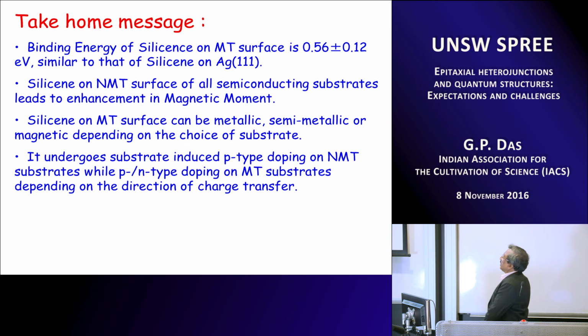So what is the take home message for this? The take home message is the following. The binding energy of silicene on metal terminated surface is coming out to be approximately 0.56 plus minus some error bar. Okay, and the corresponding value for silicene on silver 111 was 0.52. So it is close. Silicene on non-metal terminated surfaces, which are all semiconducting substrates, leads to enhancement of magnetic moment, which I showed you. In case of metal terminated surface, it can behave either metallic or semi-metallic or even magnetic, depending on the choice of the substrate. And finally, I told you that it undergoes substrate induced p-type doping on non-metal terminated substrate, while it can be p or n-type doping on metal terminated substrates. It depends on the direction of the charge transfer.